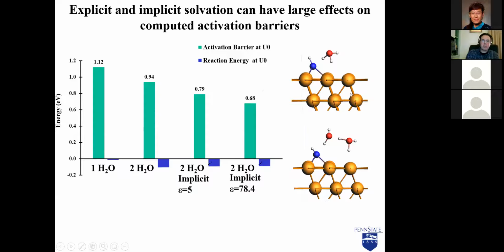Here I show you just whether or not when we look at that transfer, we're forming an NH bond here on a rhodium surface. The involvement of water, we can have that H3O+ transferring that proton. We can put 2 water molecules in there. We could put more explicit waters. That doesn't seem to make much difference, but we can then add a continuum solvent, a dielectric media around here. And we see as we add more solvation, the barrier does seem to be coming down. I don't know that a dielectric constant of 78 for water is right, but this seems to suggest it's very important to look at both explicit involvement of water as well as the long-range solvation at the electrochemical interface. And we're looking at approaches in my group as well to develop to model that.